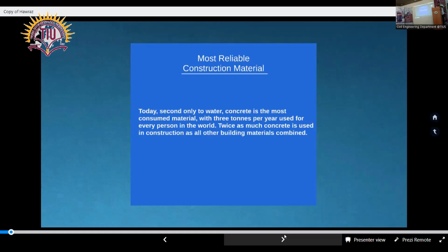and we can have normal strength concrete with compressive strength reaching 25 megapascal. Further, we can have high strength concrete, which has a compressive strength between 50 megapascal to 200, or ultra high strength concrete having a compressive strength more than 200 megapascal. This material is a versatile material. Apart from that, you can design different types of concrete. This material can be constructed in different shapes because it's cast on site.